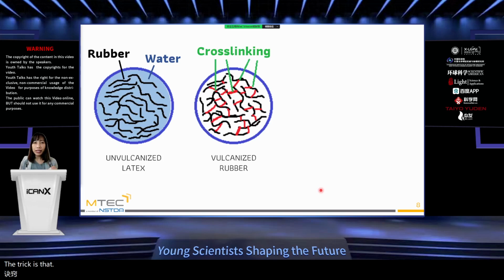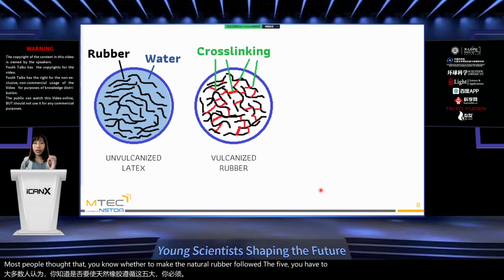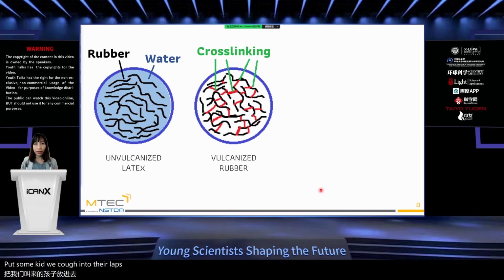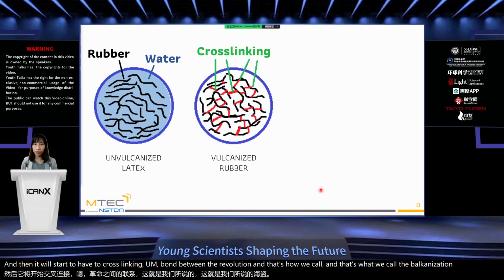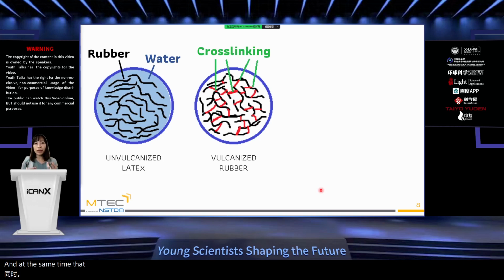The trick is that most people thought that in order to make the natural rubber solidify, you have to put some chemicals into the natural rubber latex, and then you need to give it pressure and higher temperature, and then it will start to have the cross-linking bonds between the rubber chains, and that's what we call the vulcanization process. And at the same time that they start cross-linking, the water needs to be removed from the system. So this is a very conventional way of how you produce a natural rubber product out of the latex.